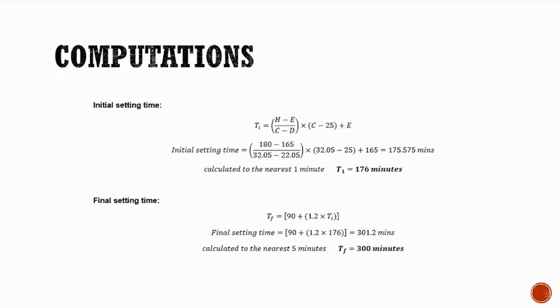For the final setting time, we will use this formula: 90 plus 1.2 times our initial setting time. So 90 plus 1.2 times 176, it will be 301.2 minutes. So based again on our ASTM C191, it should be rounded to the nearest 5 minutes. So therefore it will be 300 minutes. That all will be for our computation.